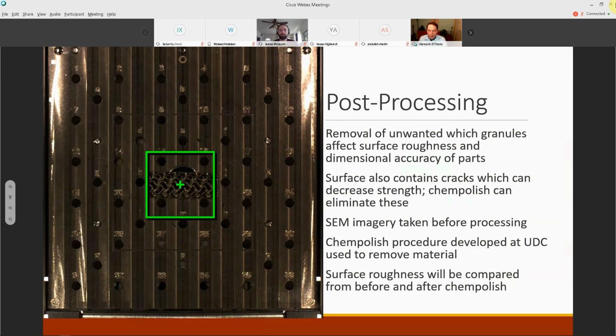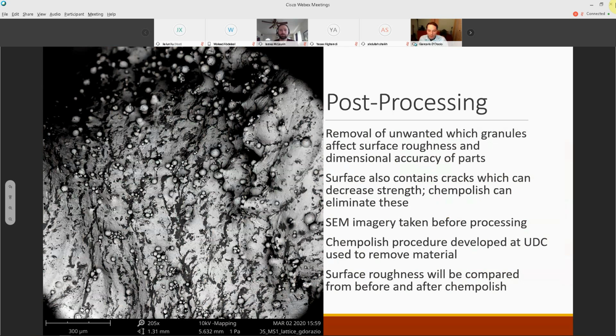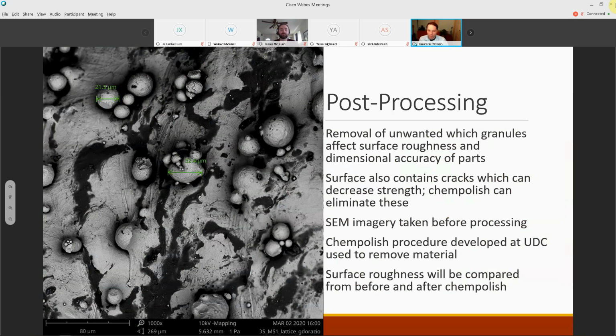You can see on the platen our part in the SEM. This is a 205 times magnification of the part. You can see a large number of granules all over the surface of the compressive test part that we have here. Zooming in a little more, at about 1,000 times magnification, you can see we have a lot of particulate between about 5 and 30 microns in diameter, and this was pretty uniform over the entire surface of the part.